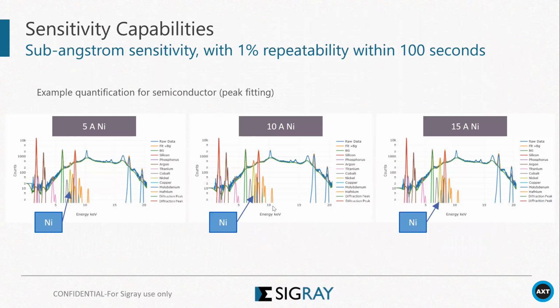So in this slide, we put a standard nickel film on top of a silicon wafer. From 5 angstrom to 10 to 15 angstrom, we have very good signal, and we have data analysis capability to do data fitting on the fly. We do this repeatedly, and within 100 seconds, we can get 1% repeatability. There's no laboratory system capable of doing what we do.